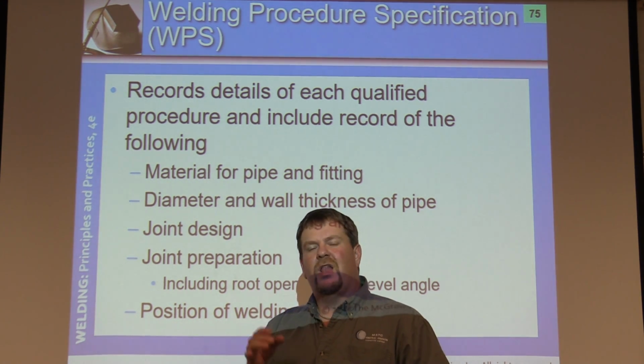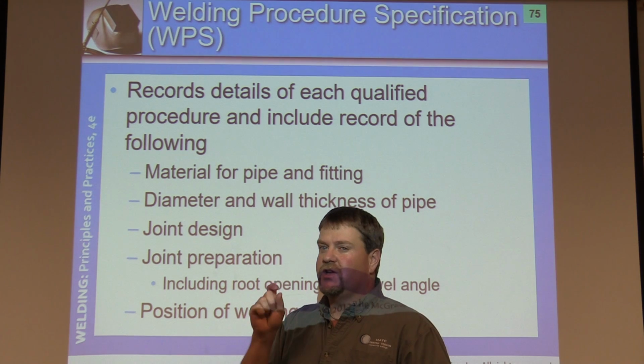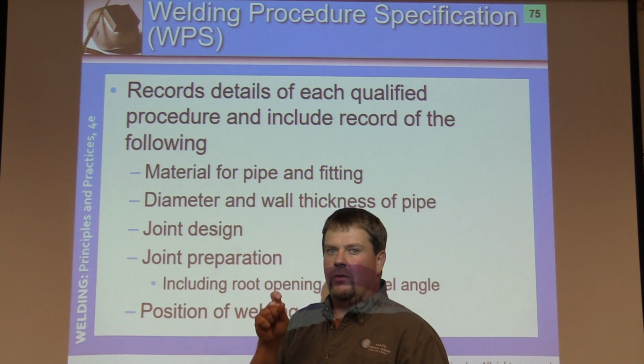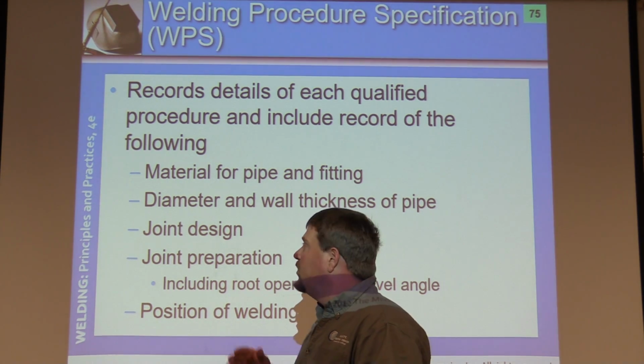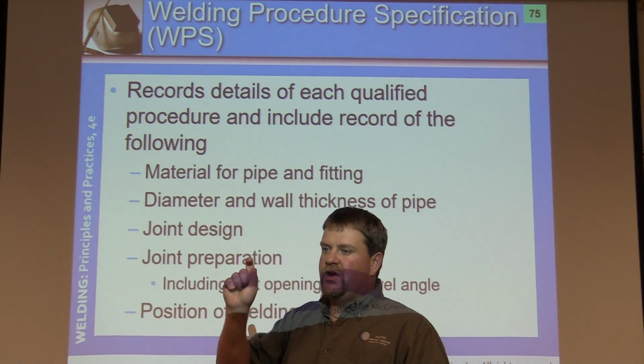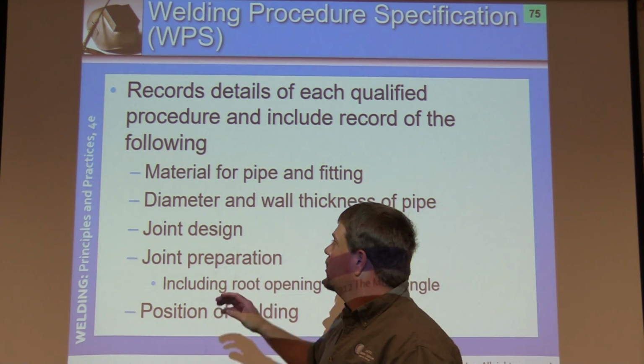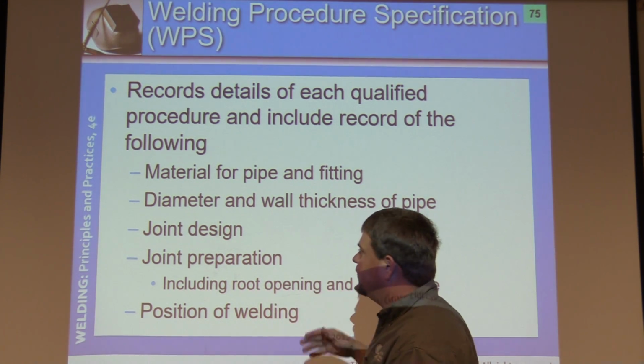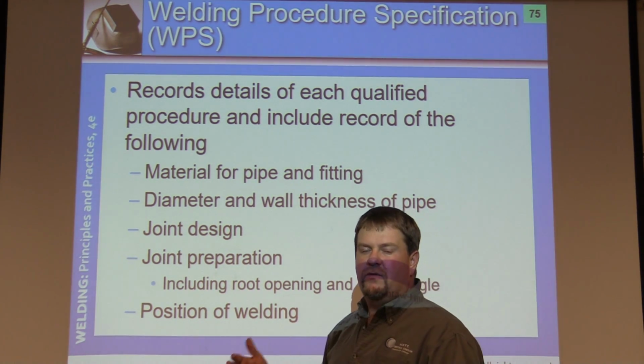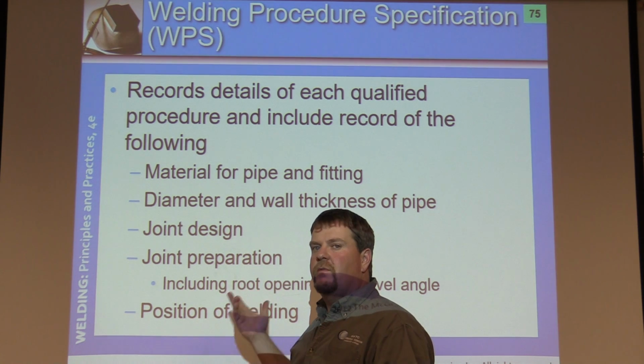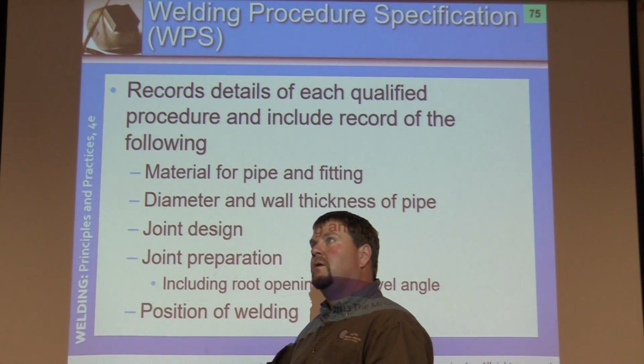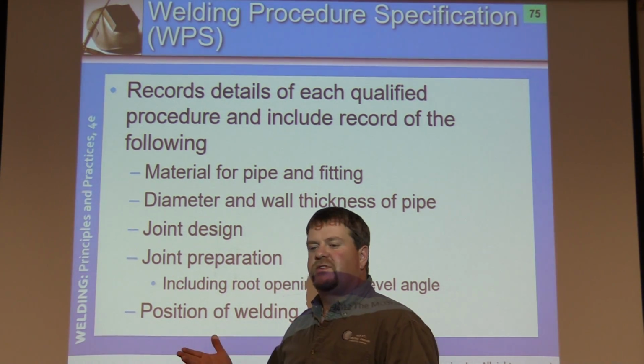a super coupon, you're allowed to go up to, so a super coupon is going to be 5/8 inch thick wall, a real heavy wall material. If you weld that out and you pass that test specifically, then you're allowed to weld up to 1.5 inches thick, from 1/8 of an inch thick to 1.5 inches thick pipe wall, any diameter. Any diameter whatsoever. That's why it's called a super coupon. If you can pass it, for most common weld purposes, most common piping systems and sizes, you're going to be able to weld all of those. Okay?